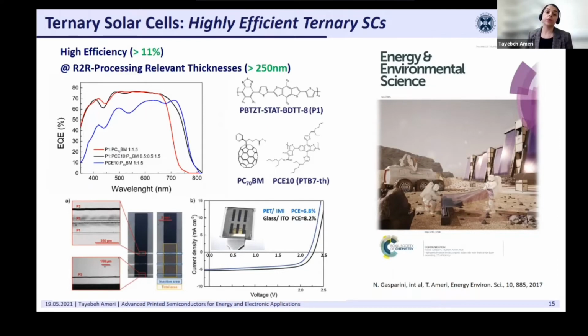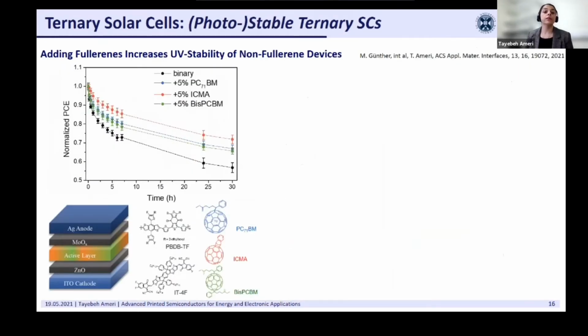However, in addition to the performance improvement, very recently we have demonstrated that this ternary sensitization can also have a significant influence and improvement on the stability of our solar cells. Here you can see, for example, when we introduce any of those fullerene derivatives as the ternary component to a host system based on this benzodithiophene polymer blended with the very well-known non-fullerene acceptor IT4F, then we significantly improve the photostability of our devices.